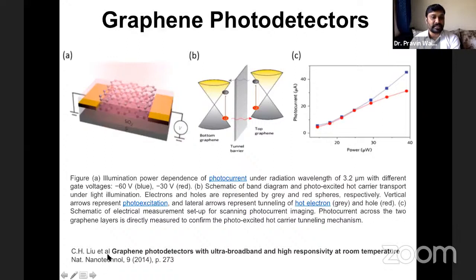Liu et al. published this work in 2014 in Nature Nanotechnology. What they have done is simply use two graphene layers separated by a thin tunnel barrier, right? And the performance of this photodetector can be tuned by changing the tunnel barrier. So if you change the tunnel barrier, you will find that the performance of the photodetector can be tuned, right? In the first figure, you can clearly see the illumination power dependence of the photocurrent in C under the radiation wavelength of 3.2 at different gate voltages. So in the graphene, there is the energy of the graphene here.